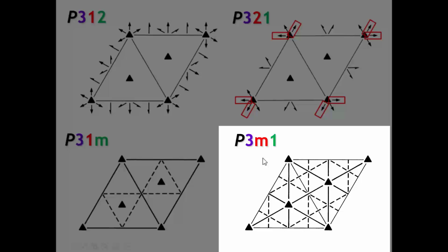So where are the mirror planes? Right, so these are going to be planes that are perpendicular to the A and B directions. And here they are. These vertical mirror planes are perpendicular to A. These mirror planes here are perpendicular to B. And both for the 2-fold rotations and the mirror planes, we have a third one that's not perpendicular to A or B. Because of the 3-fold rotation axis, we have to have mirror planes that are at 120-degree angles to each other.